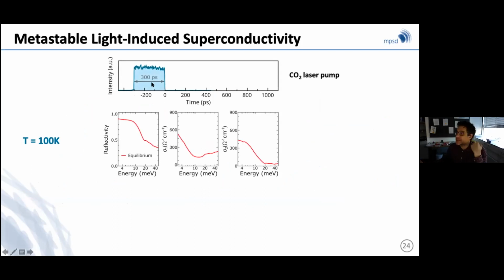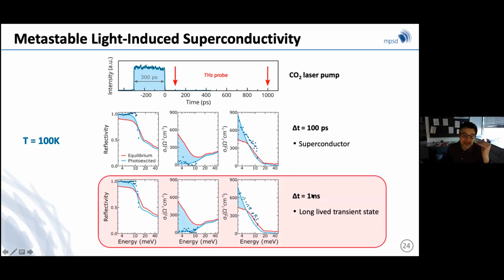And so he could do experiments in which now, instead of having a 100 femtosecond pulse, he could drive this with a pulse that was 3,000 times longer or 10,000 times longer, up to a nanosecond. And again, at 100 Kelvin, so 5 times above equilibrium TC, lo and behold, what he discovered was that already 100 picoseconds after the drive pulse was terminated, he could still obtain optical properties that were compatible with the appearance of a long-lived superconducting state, which no longer disappears in 1 picosecond, but lives all the way to 1 nanosecond. Actually, 12 nanoseconds is the lifetime that we find.